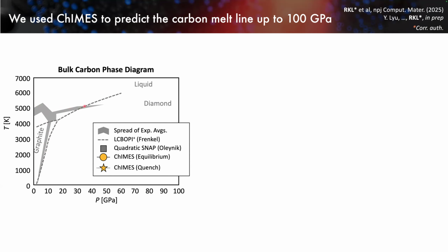For the diamond melting portion, it seems like the data is tapering off at high pressure. This is not because the experiments are getting more precise—it's because there is one experiment reported at this highest pressure, two experiments here, and so on. More importantly, the specific temperatures are not measured in those experiments.